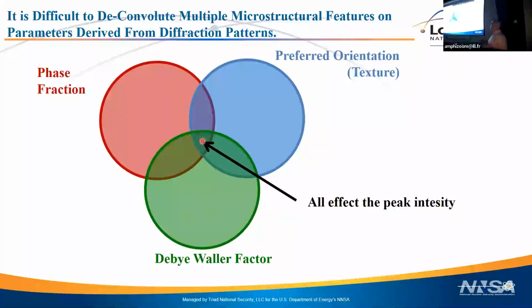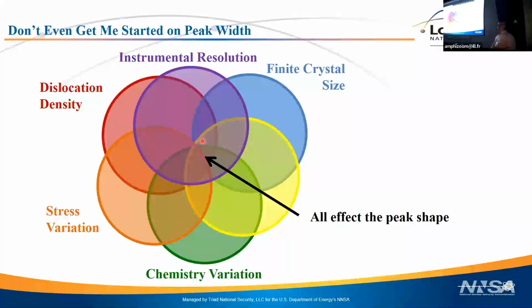You have phase fraction, you have texture, and you have the Debye-Waller factor, if you're up close to the melting point. At room temperature, the Debye-Waller factor is usually not a problem, but if you're at, say, 80% of the melting point, it becomes relevant. All of those things affect the peak intensity, and if you don't do enough measurements with enough quality, you can't separate them. And don't even start about peak width, right? The things that contribute to peak width are just an endless list. So deconvoluting all these effects is a lot of what I'll talk about.